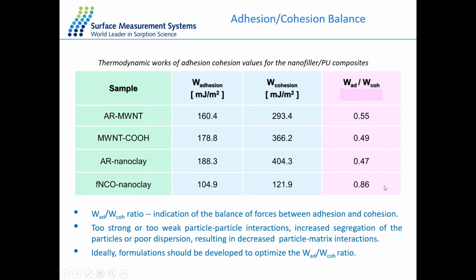So what we've done is calculate the work of adhesion, the work of cohesion, and the work of adhesion to cohesion ratio for each of our samples. And it's quite interesting because what we tend to do is understand the work of adhesion to cohesion ratio to understand the difference between our samples in the case of formulation. If the work of cohesion is too strong, it may lead to aggregation, poor blending, and poor composites for our nanofillers. So it's a very good technique to optimize this work of adhesion to cohesion ratio, which is what we've done here.